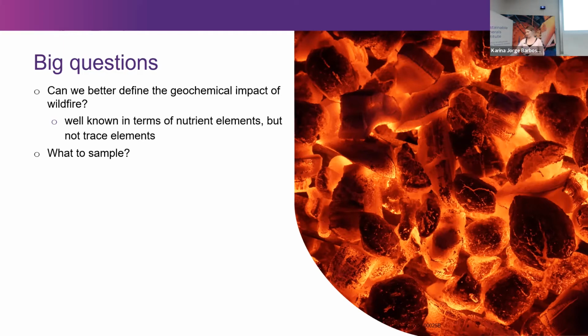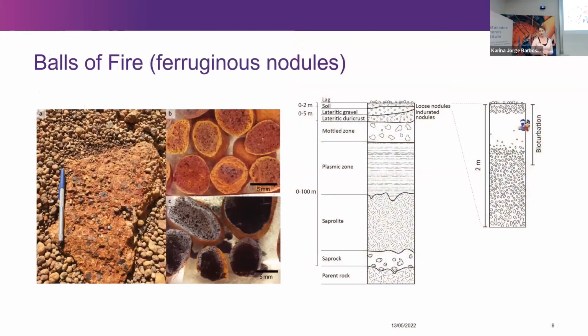So this is where the balls of fire come in. Balls of fire are ferruginous nodules. And these little guys occur in the top of a weathering profile. So coming back here in the upper couple of meters in the soil, or if there's no soil, they can form at the top of that duricrust in the weathering profile. And these guys have a really nice, typical low temperature weathering mineral assemblage. So they have things like iron oxides, they can have gibbsite, they have clay minerals, they have quartz. And they're these really hard, durable, handy little packages that don't tend to get broken. They don't tend to get weathered very easily, and they come in magnetic and non-magnetic varieties. Surprise, the magnetic varieties are quite commonly cited to have been caused by fires.